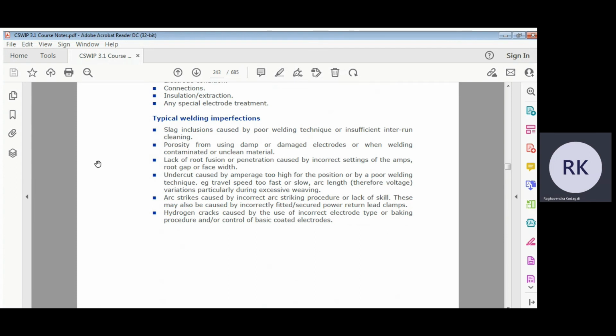Slag inclusion caused by poor welding technique. Slag is a very common issue. If they are not doing the inter-run cleaning, slag will remain in the welding and it will show up in the radiography. Porosity from using damp or damaged electrodes and when welding contaminated by unclean material. So we have seen that when the wind is also there, the porosity comes, or if the electrode is not good also, porosity will come.